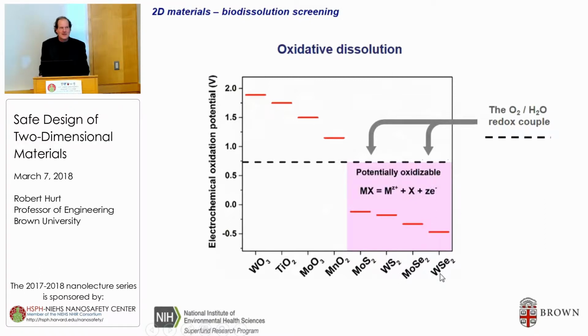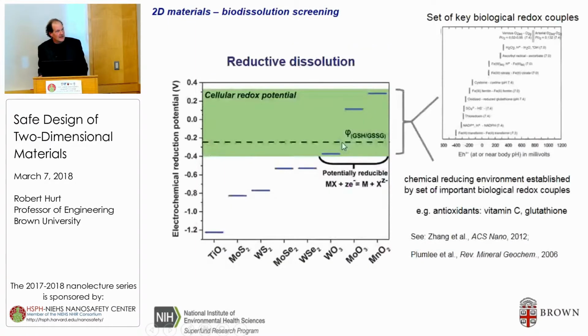And that's true for molybdenum disulfide. It's true for the whole class of transition metal dichalcogenides, the so-called TMDs. This is the most important class of material after graphene, I would say, in the 2D material world. They're highly insoluble, but they're all potentially oxidizable. It's not clear that they're stable. Now, manganese dioxide, we still have that. That one is predicted to stay around as a solid, you would think.